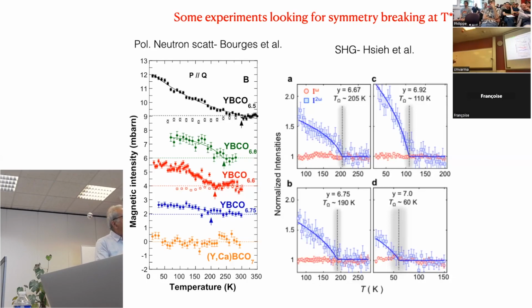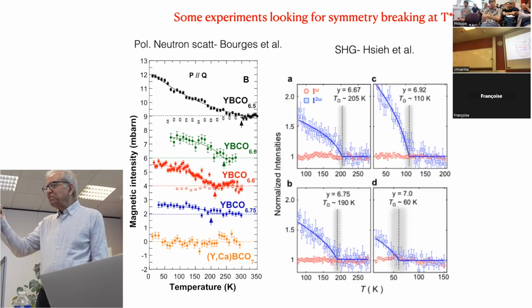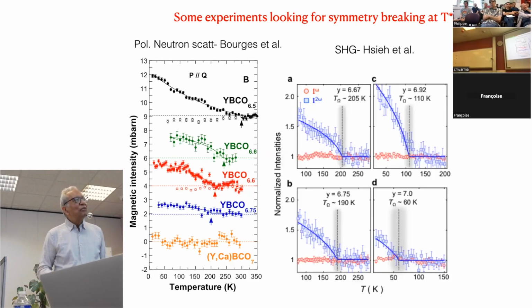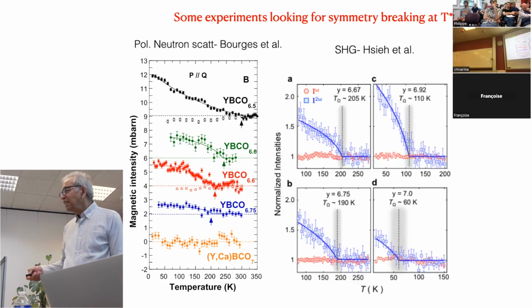On the same samples at somewhat similar doping, many years later, I think this started around 2005. This happened around 2011. This guy at Caltech did second harmonic generation. That goes to your statement about symmetry, center of symmetry. There's a center of symmetry, so there should be no second harmonic generation, but doing that in a metal is not easy because the surface breaks it, right. And you have to be very careful what you're doing. And they found that there was an extra signal. You see that? There's already some second harmonic generation, and then something increases, and this increase happens at a specific temperature, which, if you interpolate between these things, you'll find is within 10 degrees the same.